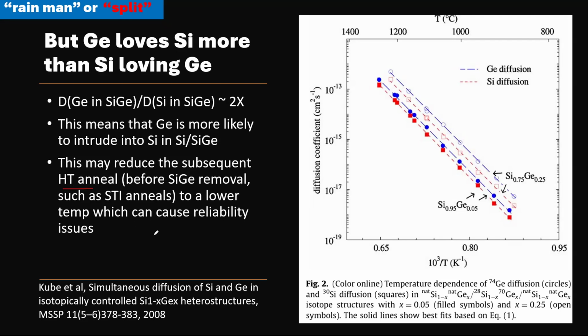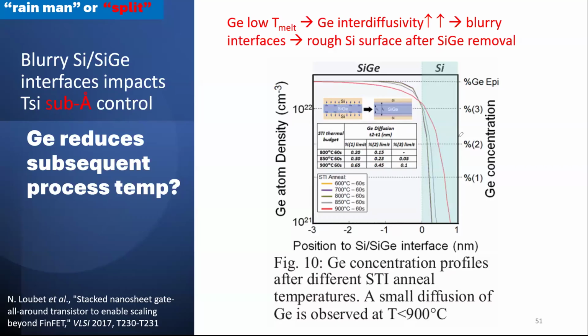Because many high temperature anneals, before you remove the SiGe, remove the sacrificial layer, for example, STI anneal, you cannot use high temperature. IBM showed that. IBM said, what, this silicon, SiGe, see, germanium coming in, right? Coming in. Higher percentage. Because STI temperature, 900. Actually, STI temperature 900 is kind of low. It depends on process. Some people use 1000, spike anneal, super high temperature. Because you need to form a beautiful oxide. That's what STI means. Shallow trench isolation. That liner, so it's just not the STI. This STI anneal meaning is anneal for liner and anneal for the bulk.